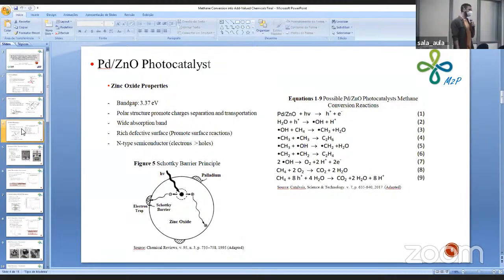Talking about the chosen semiconductor, we have zinc oxide, and it is a common photocatalyst given its similarity with titanium dioxide, which is the base material for photocatalytic studies. Some of its properties are favorable for photocatalysis: its polar structure can promote charge separation and transportation along the semiconductor particle. We have a wide absorption band and a rich defective surface that can promote more surface reactions to occur. And besides that, we have the palladium nanoparticle deposition that can act as a co-catalyst.